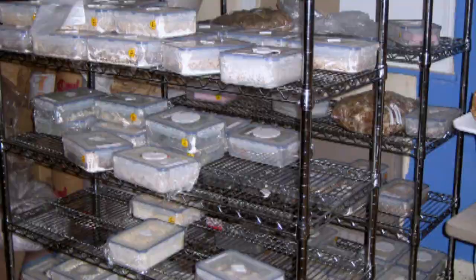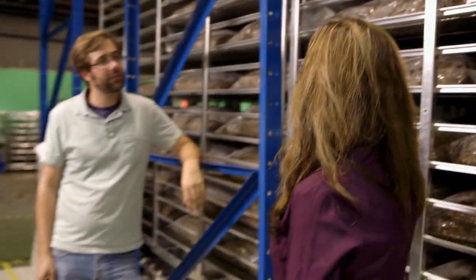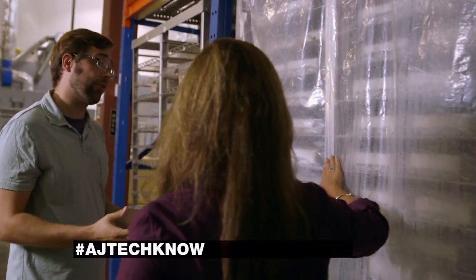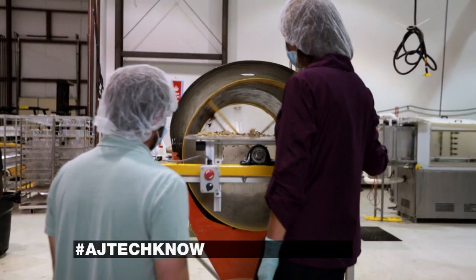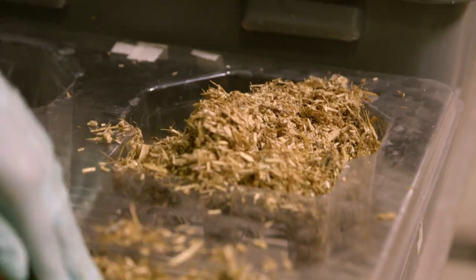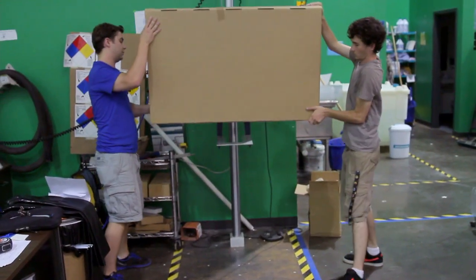This is where it all starts with this farm waste. It actually takes close to seven days for a product to be grown from beginning to completion, but we're about to show you how it works in seconds. The waste is first cleaned right before adding the mycelium, then it gets incubated for about two to three days and becomes a solid white mass. Next, it goes through a trommel, a machine that grinds the waste into a type of mulch so it can be packed into the molds. The molds are then stacked and left for another three days, where the mycelium does what the mycelium does — grow. All that's left is to bake it at a low temperature of 200 degrees to stunt the growth of the mycelium, so it can be sold to corporations like Dell Computers and other Fortune 500 companies.